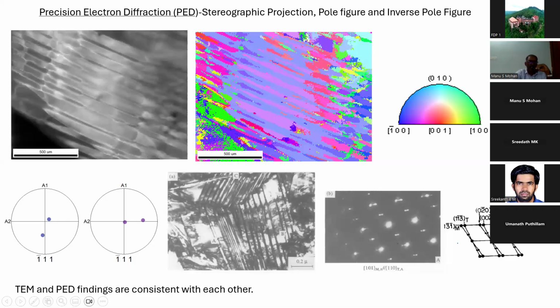And then when I looked at the literature carefully, I observed that the common crystallographic plane to these laths - you see some parallel laths - is nothing but bar-111. Which is that plane here? It is actually the plane I asked it to plot for both the maroon color and the blue color. When I was plotting, I observed that both are very close, meaning the TEM diffraction pattern and the PED data are consistent - the twin plane is confirmed as bar-111.